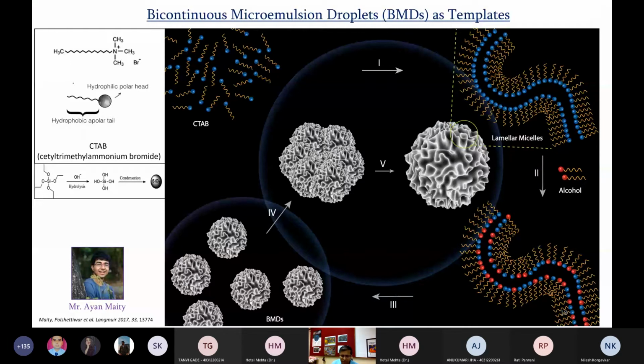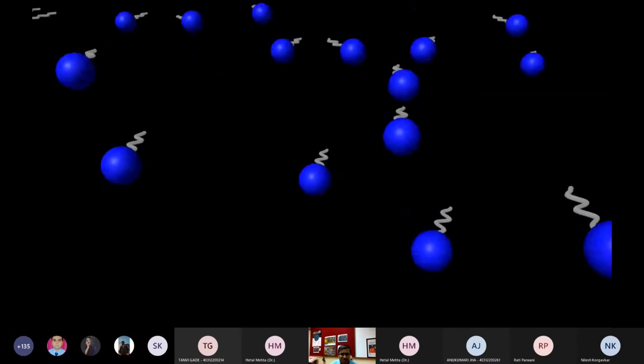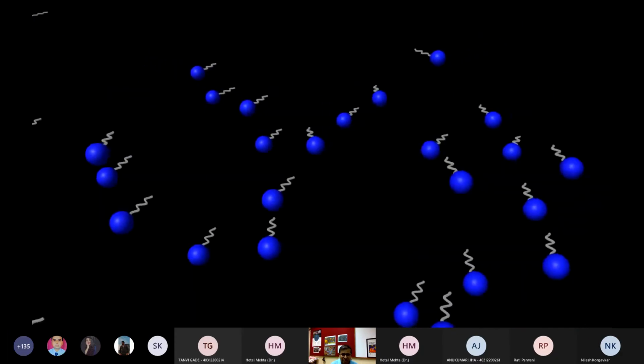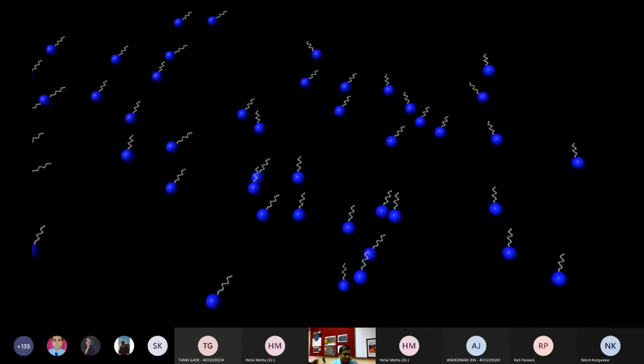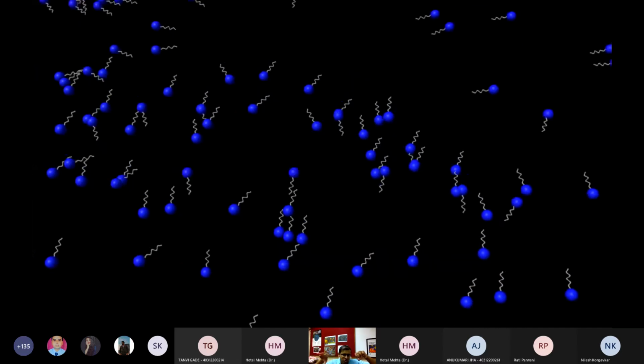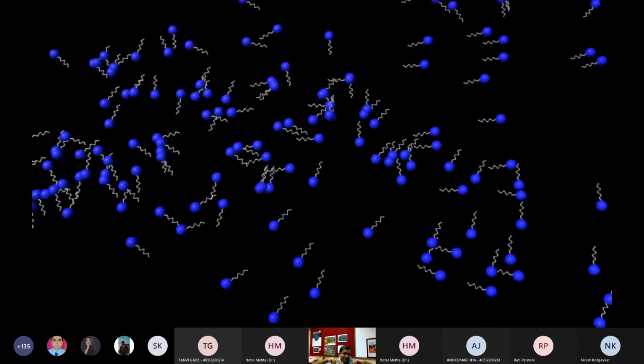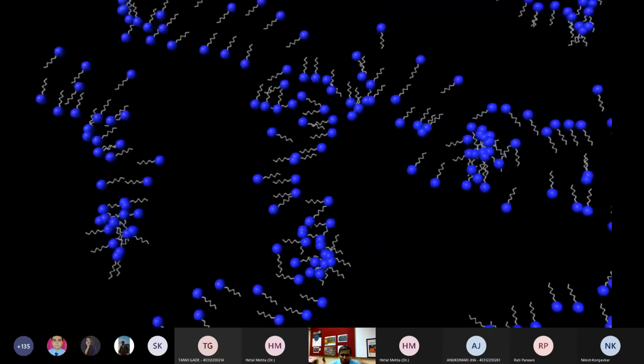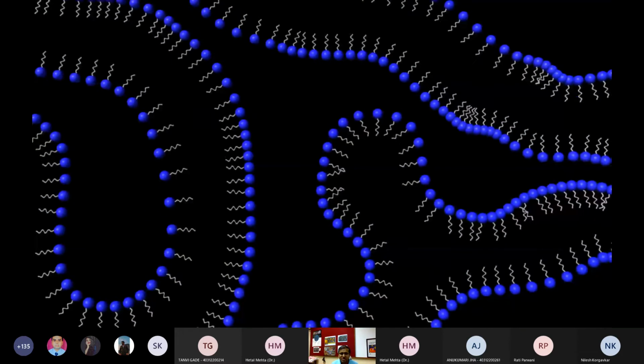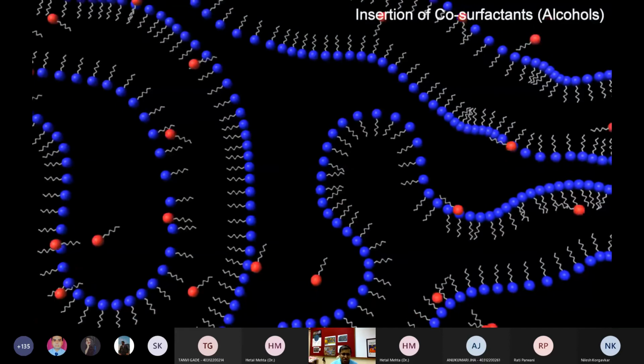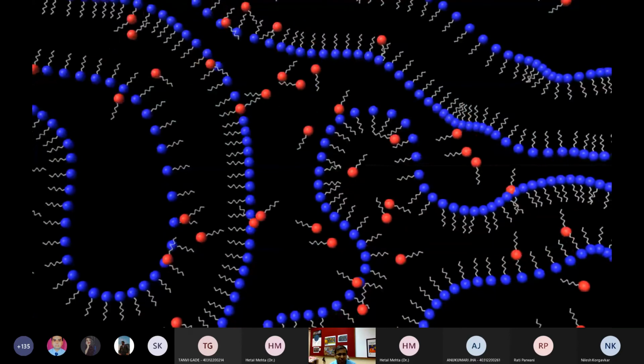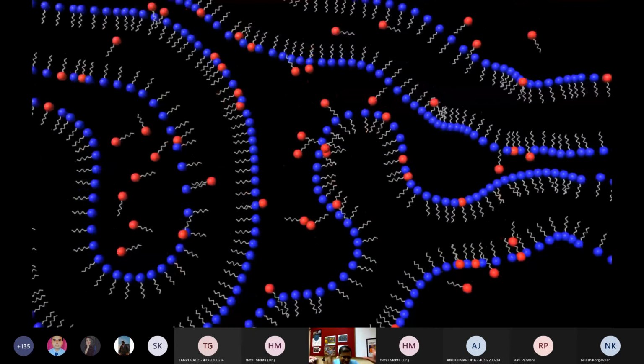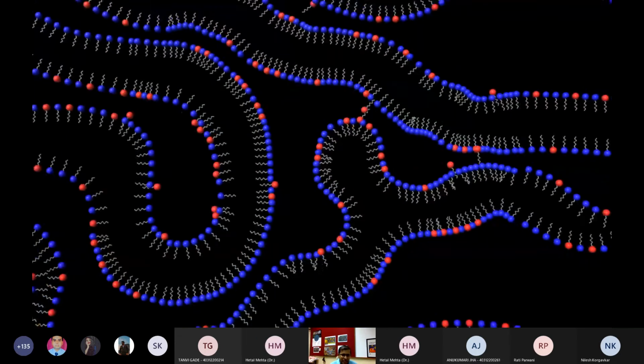And then we also tried to understand the formation mechanism of the material. Why do I form those spheres? Why not some other shape and morphology? The synthesis was carried out using a templated approach. Templates are molecules, in this case CTAB, a quaternary nitrogen and then a C16 chain. The blue ball is the quaternary nitrogen. The zigzag line is the carbon chain up to 16. So polar, non-polar, we added them into the solvent. They form these lamellar phases because we are using high concentration. Then we add one more molecule, pentanol or hexanol. These are called co-surfactants, which stabilize these interfaces, make them rigid and stable in the solvent.